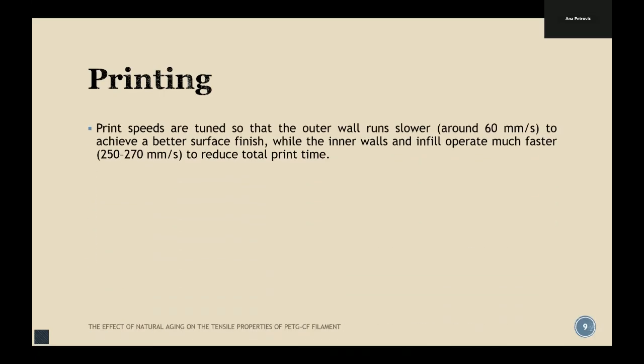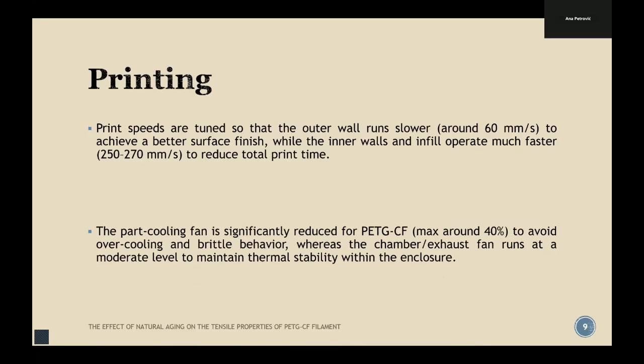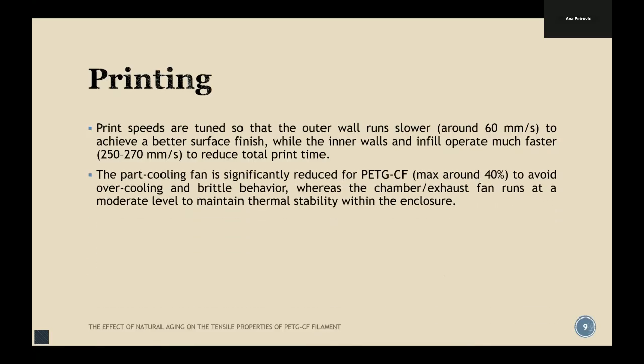Print speeds are tuned so the outer wall runs slow, around 60 millimeters per second, to achieve a better surface finish, while the inner walls and infill operate much faster, 250 to 270 millimeters per second, to reduce total print time. This is done to be closest to real scenarios. The part cooling fan is significantly reduced to a max of around 40%, to avoid overcooling and brittle behavior